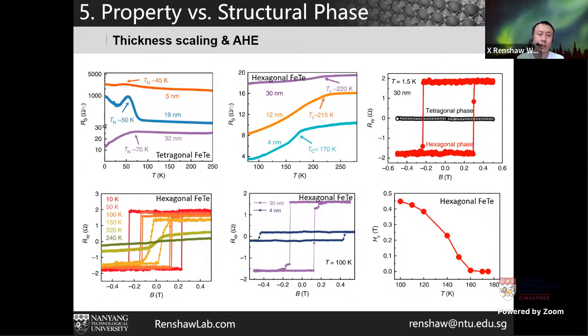This is also consistent with other material systems, for example, oxides, which I worked on a lot. If we talk about the hexagonal phase, which is ferromagnetic, at 30 nanometer thickness the TC is around 220 K to be specific. And if we lower the thickness down to, for example, 4 nanometers, its TC is 170 K. It's also a bit lower, but luckily it still survives.